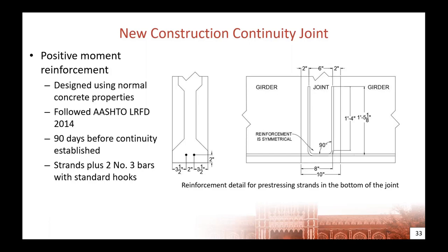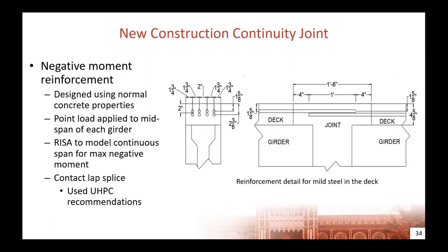And what we came up with was needing two pre-stressing strands coming out of each beam going into the joint and two number three bars with standard hooks with an extension that was based on the AASHTO LRFD specifications and conventional concrete. For the negative moment reinforcement, we used conventional mild steel and moment demands based on failing a two-span girder system in the girder at mid-span. So with a point load applied on each span, we modeled it as a continuous system, came up with our negative moment demand, and found the amount of reinforcement that was needed in our joint. We then designed the splice for that reinforcement using UHPC recommendations for the negative moment.